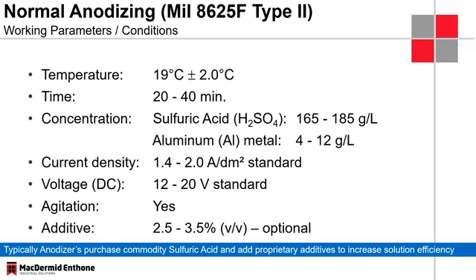The current density here is around 1.5 amps per square decimeter. That's pretty standard. If we go much higher than that, we'll see a burn on the components, which looks like a white dusty deposit, which can be seen after anodizing or after sealing on the components. Voltage 12 to 20 volts, pretty standard. Depends a little bit on the jig material we use. Generally speaking, aluminum racks, aluminum jigs have a slightly lower voltage because of the better conductivity compared to titanium racks.